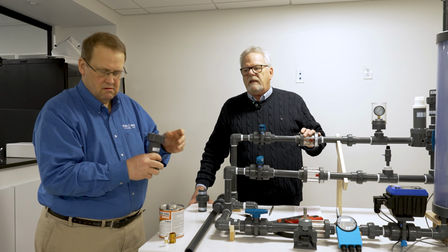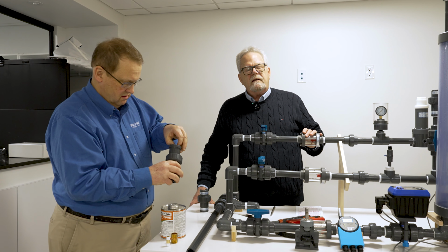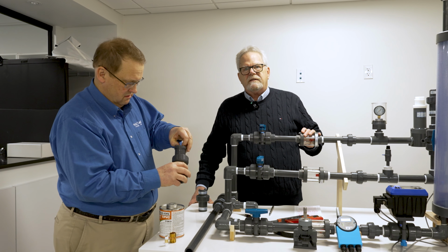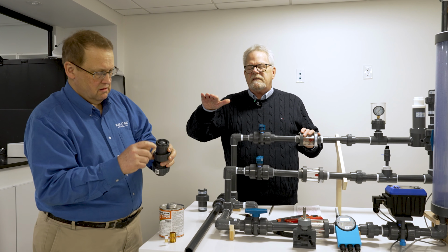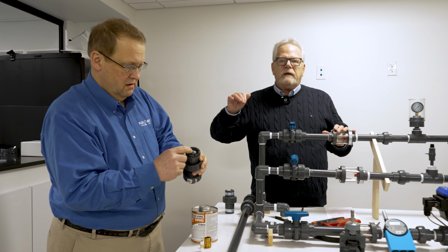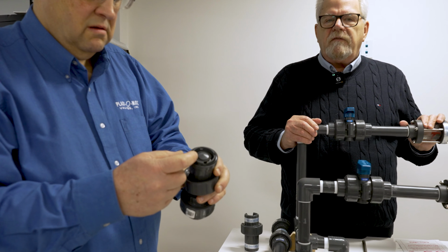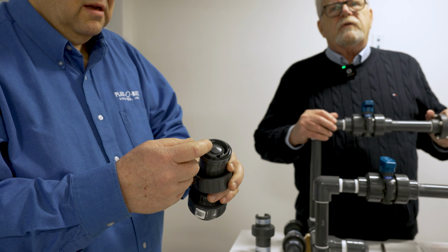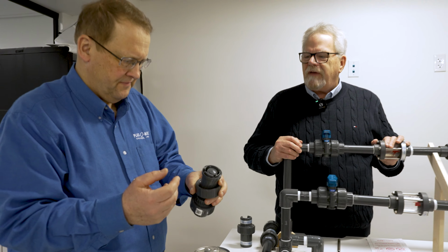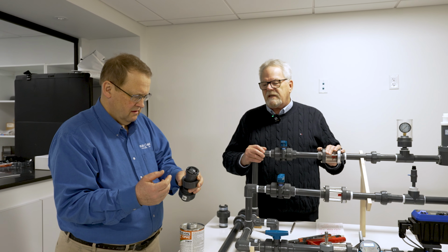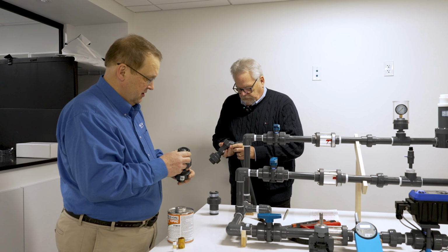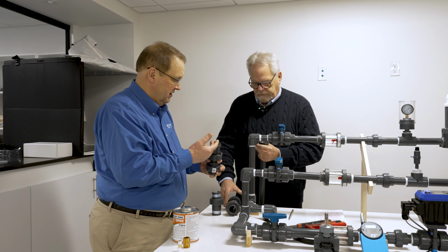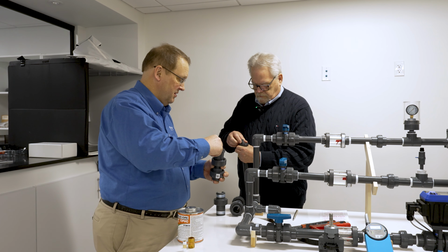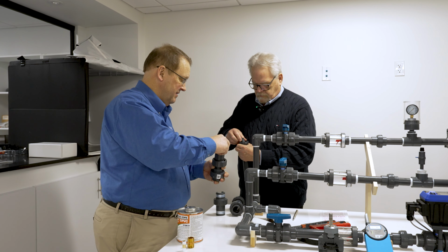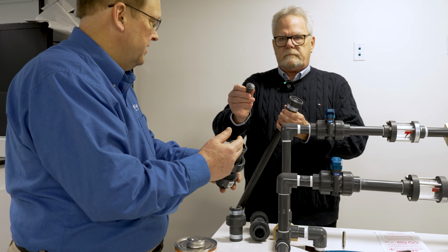They let the joint dry, and in the drying process, it found its way in between the seat and the orifice. So when they pressure tested the assembly, they found that it leaked. Of course, the first thing they said was, you didn't QC test your valve, Plast-O-Matic, but that's not the case at all, because we test every valve that we manufacture. So what happened is you found that they had dripped solvent cement into the body of the valve itself and actually welded components together inside the valve.